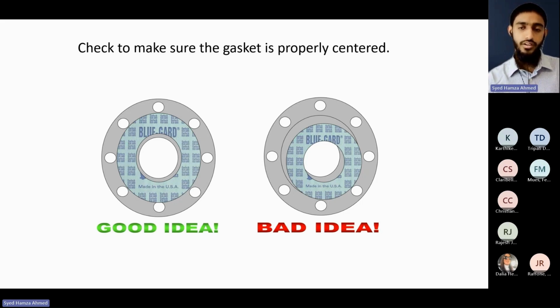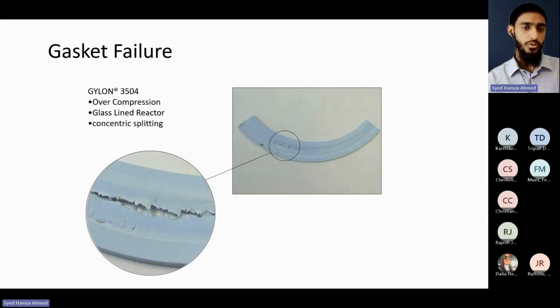Some failures of an incorrect type of gasket being selected can be due to overcompression. This is Garlock's Gylon 3504, a type of gasket which has been overcompressed in a glass line reactor. So we can see concentric splitting here due to overcompression. This is probably due to improper installation practices where the torquing values as recommended by the gasket provider were not utilized by the people installing the gaskets.